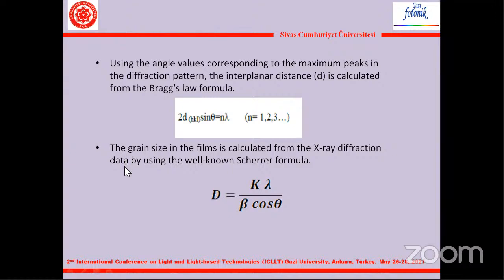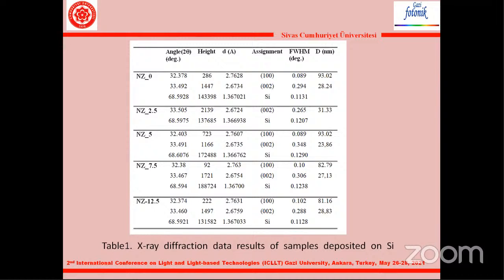The grain size in the films is calculated from the X-ray diffraction data by using the well-known formula, where K is a constant, lambda is the wavelength of the X-ray used, theta is the Bragg reflection angle, and beta is the half maximum width of the reflection in radians. For calculations, the K constant is taken as 0.9. Table 1 shows the XRD data results of the samples deposited on silicon. In zinc oxide thin films doped with different nitrogen percentages, as the percentage of nitrogen increased, excluding the undoped sample, the 2 theta angle decreased.